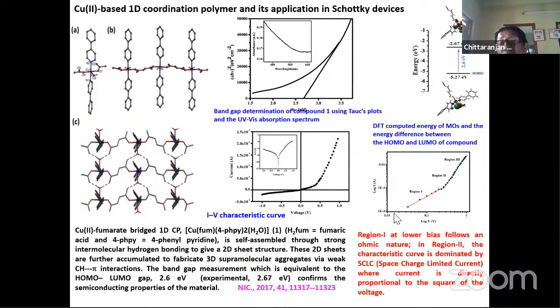Besides, the plot of log I by log V, and the potential current plot shows three different regions. You see, region one is the common relationship, that is the ohmic relation between current and voltage, where I varies as V, while in region 2 and region 3, current is increased, and it is not a simple V varies as I. Rather, here I varies as V square in case of 2, and in case of 3, I varies as V to the power 2.6.